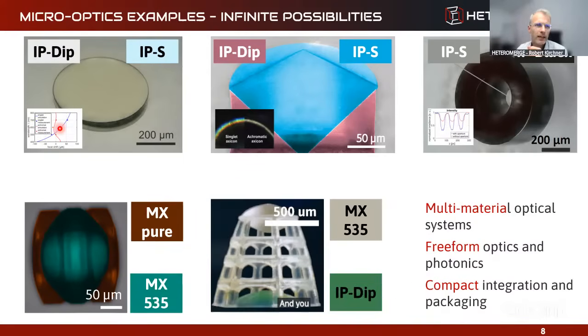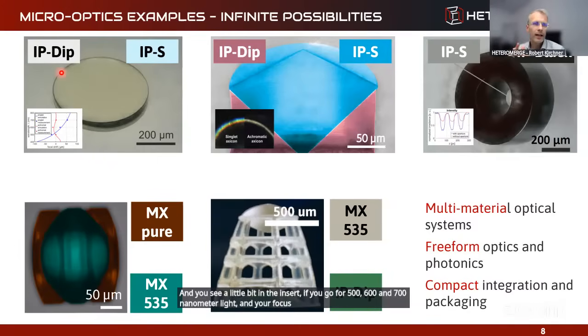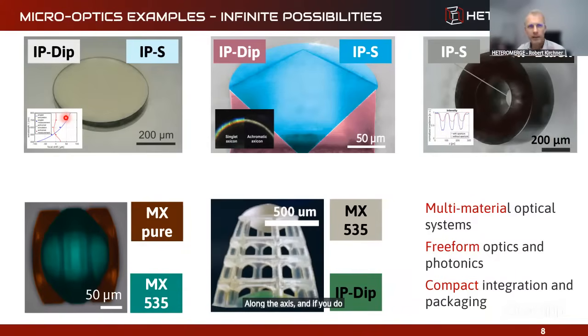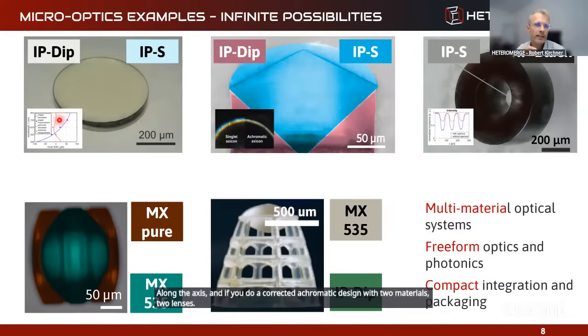And you see a little bit in the insert, if you go for 500, 600, and 700 nanometer light, and you focus through a single lenslet, so a singlet element, you will get a rather strong focus shift of about 25 to 50 micrometer along the axis. And if you do a corrected achromatic design with two materials, two lenses, you focus for, in this case, 700 nanometer and 500 nanometer. The 600 nanometer is not fully corrected because of the two materials, two lenses you have available. But it's much better.